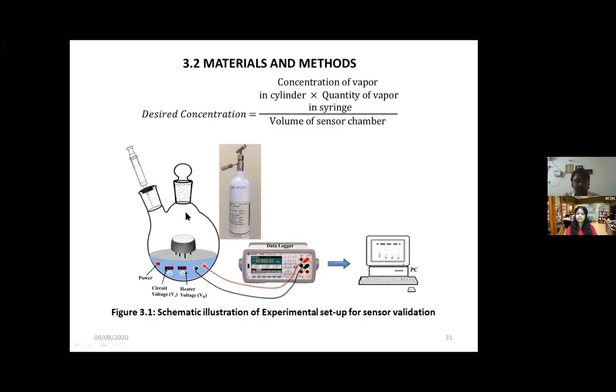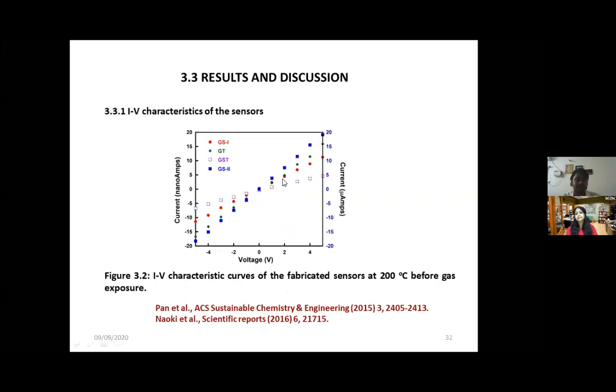So when it is infused, there is a change in resistance. This is the Keysight data logger, which has a measuring range between a few mega ohms to 1000 giga ohms, and this has been connected to a PC to observe the change in resistance after the infusion of acetone from the baseline resistance. So this is the schematic of the static gas sensing setup. We fabricated our sensors and validated them based on the static gas sensing setup.